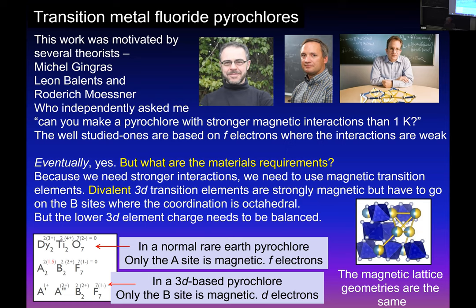So basically, it's a crystal structure type. Yes, what I didn't explain too well is that pyrochlore is a particular structure type. Pyrochlore is the actual mineral, but the pyrochlore structure type is A2B2O6 with an extra vertex. And there's something very peculiar about the pyrochlore structure: not only is the rare earth lattice a lattice of decorated diamond, where you put an extra magnetic vertex, but the non-magnetic part is also corner sharing tetrahedra. So the pyrochlore structure is very special. It's made of two interpenetrating tetrahedral lattices sharing corners with each other.